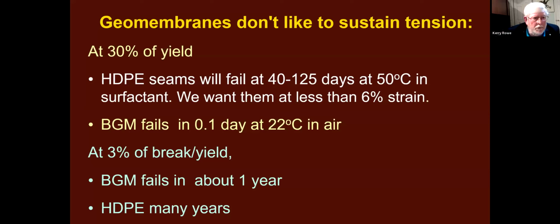Now, remember, Eric showed a dramatic drop as the temperature goes up from room temperature to 50 degrees. So this is being very generous, relatively speaking, to the BGM. At 3% strain, we got breaks in about 1 year projected from the curve I saw. We've never seen one at that strain for an HDPE seam. We've been doing tests for years now. We're expecting it's going to be probably after I'm no longer with us.